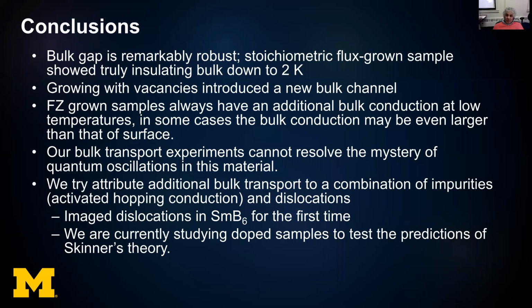So I want to conclude by saying that there are differences between floating zone and flux-grown samples. Floating zone samples have additional conduction. I don't think our experiments will, at this stage, resolve the mystery of quantum oscillations, but we are going after these disorder-driven conduction paths, both the possibility of transport through dislocations, as well as the predictions of Brian Skinner's theory.